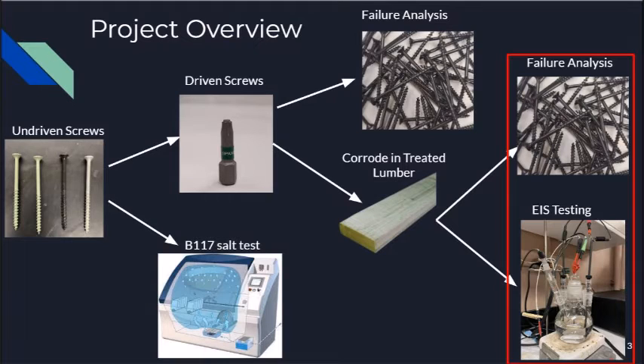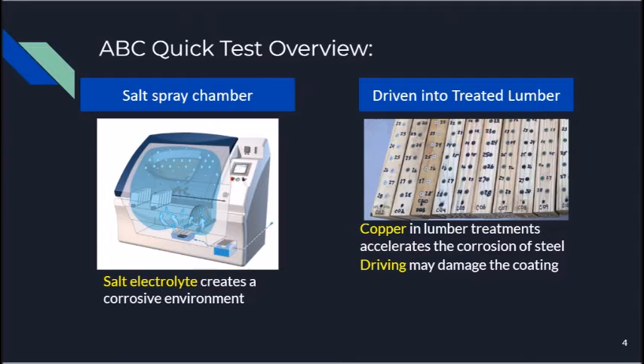It starts with screws, some of which are put through long-term corrosion tests by our sponsor, which we use for failure analysis, and others that we use for our own EIS testing. We were also given samples that had been corrosion tested in either a salt spray chamber or driven into treated lumber. These two test methods are used because the salt electrolyte mimics a coastal environment, while the lumber tests mimic more general use. It is the copper in treated lumber that is known to accelerate the corrosion of steel fasteners, while salt can increase corrosion due to the increased conductivity associated with more salt.